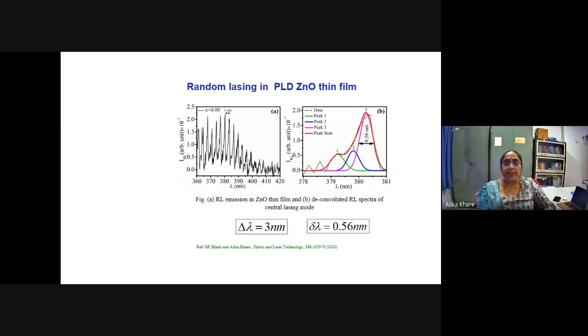Another check is in terms of the mode structure. In a laser, we know there are periodic modes, particularly longitudinal modes, which are reasonably equispaced. So here we got the spectrum of the laser, with periodic modes, and the separation between the periodic modes was around 3 nanometers.